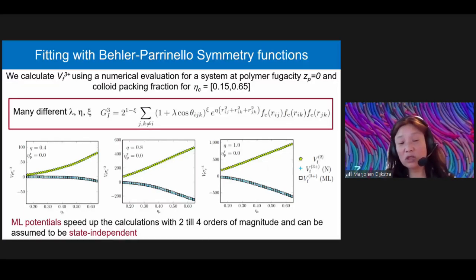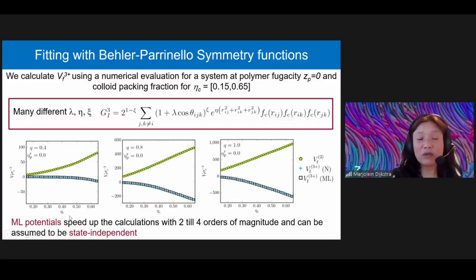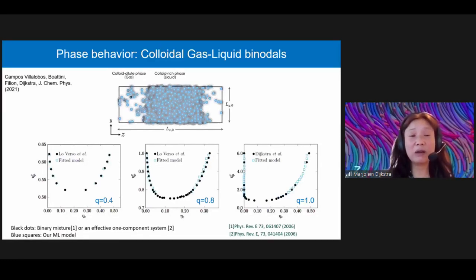So here we fit all these colloid packing fractions at the same time with the same machine learning fit. And so we can assume that this machine learning fit is state independent, and it moreover speeds up the calculations by 2 or more, 4 orders of magnitude compared to the numerical evaluation. That these machine learning fits can be assumed to be state independent is very nice, because you can now also do direct coexistence simulations in such a way that you can study the phase behavior of phase coexistence of a colloidal gas phase in coexistence with a very dense colloidal liquid phase in a single simulation box. And so that's what we have done here.